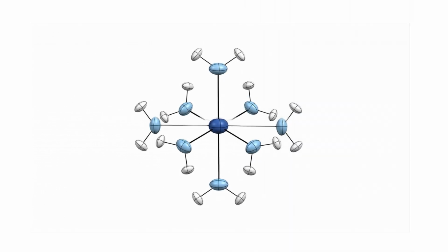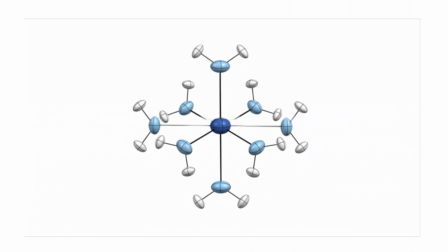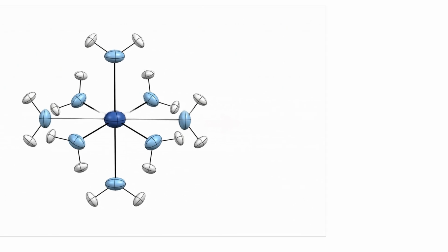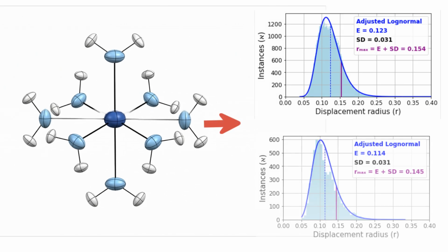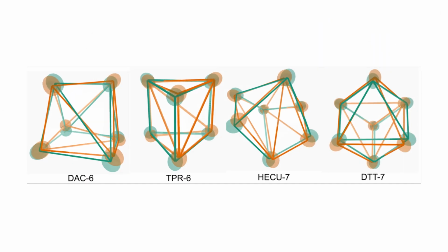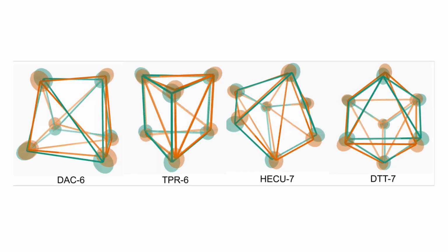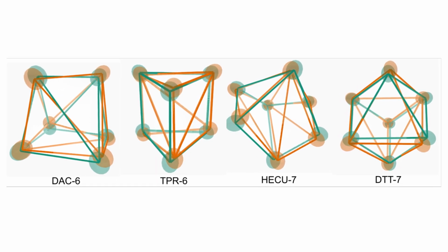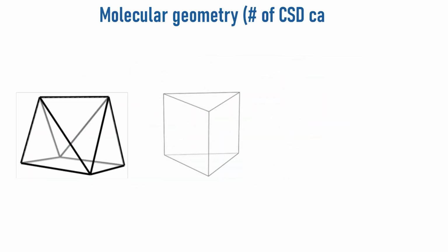Our thermal criterion was not guessed. It was derived from atomic displacement data extracted from more than 42,000 high-quality crystal structures. Using those displacement statistics, we determined which optimized geometries remain distinguishable within crystallographic uncertainty, and which collapse into the same thermal class. Then we reclassified the database.